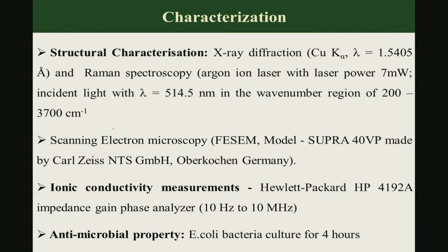To confirm whether silver is in ionic state, you can do specific optical absorption spectroscopy analysis, or other standard materials characterization like Raman spectroscopy and X-ray diffraction. Silver also potentially increases the ionic conductivity of the hydroxyapatite-based materials, and this has been confirmed using ionic conductivity measurements.